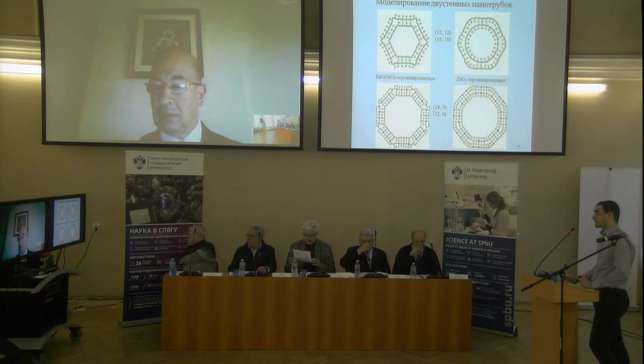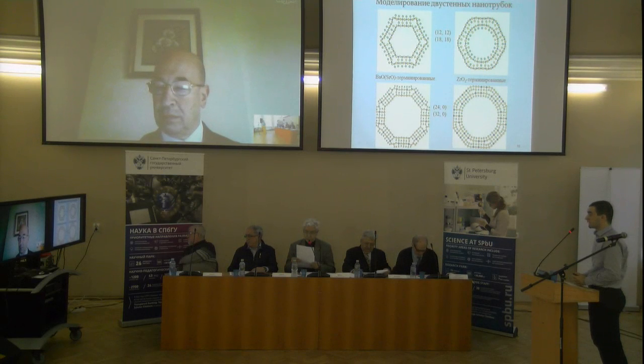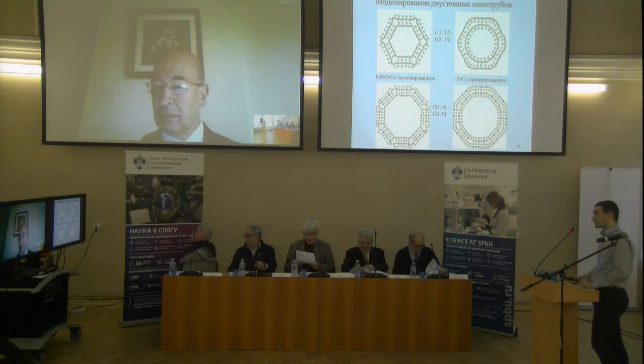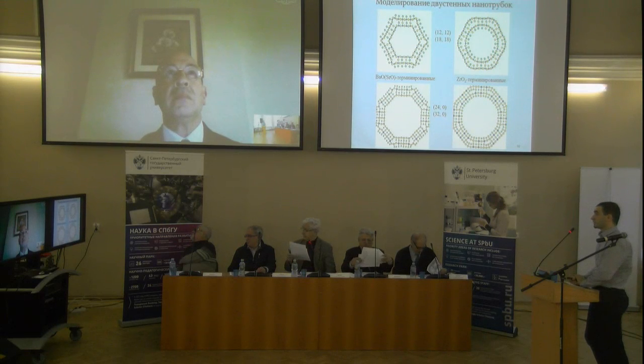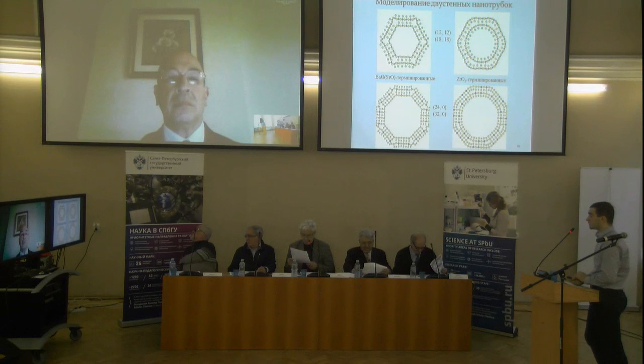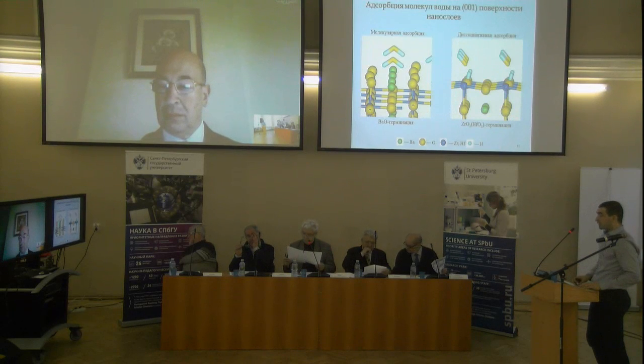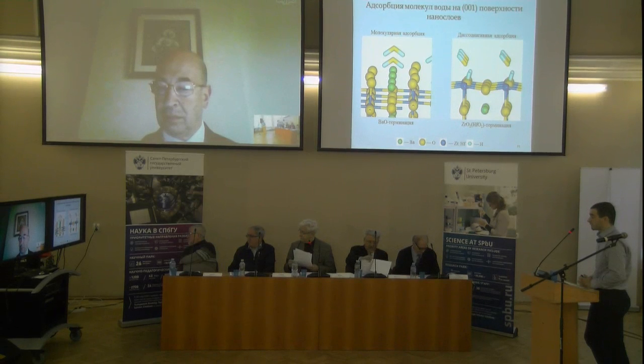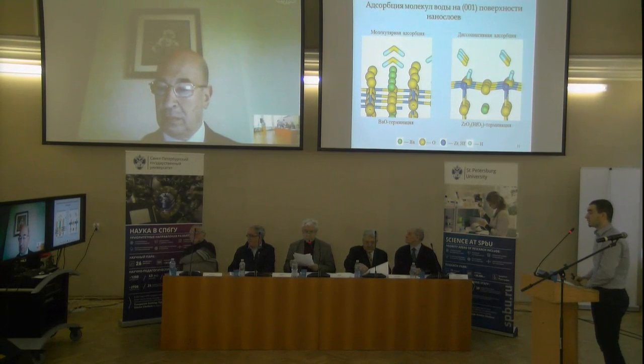To estimate the stability of stratified DWNT, the binding energies between two NTs were calculated. The negative binding energies of the constituent SWNTs suggest that stratified DWNT is energetically more advantageous than the two isolated SWNTs at N greater than 16 NTs. NTs with N smaller than 16 do not exfoliate and show high energy of formation. The stratification was not observed in the case of BaTiO3 NT, apparently due to the incommensurability of the periods of NT from TiO2 and NT from BaTiO3.